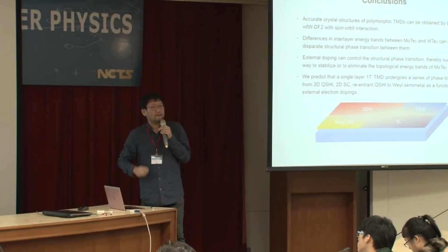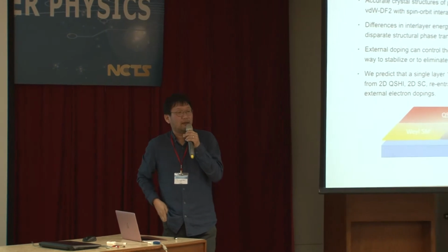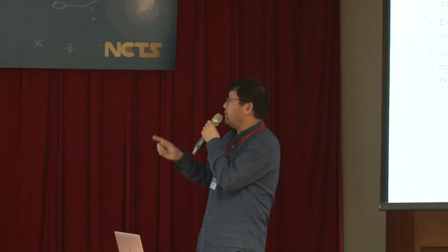Okay. But I'm asking about this Weyl semimetal phase. In the Weyl semimetal phase, actually it doesn't change. It actually modifies the interlayer interaction a little bit. Then the distance between the 2 Weyl points gets closer and closer, and they just annihilate each other. But in 2D, I mean, the Weyl node can get gapped without the merging of the pair.